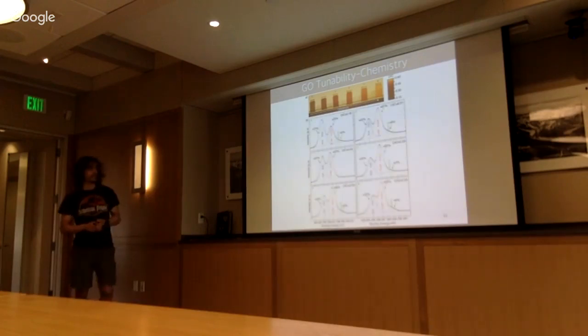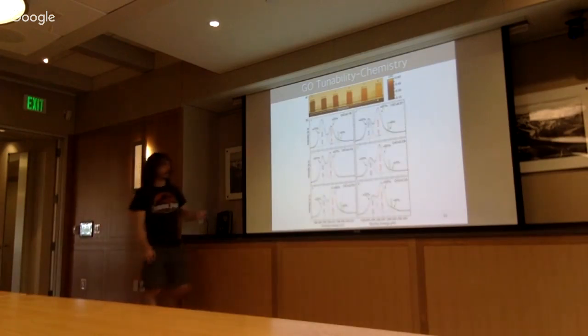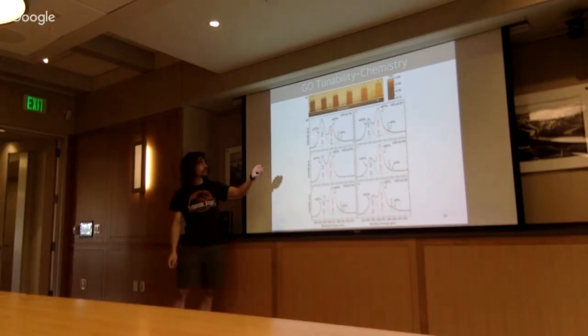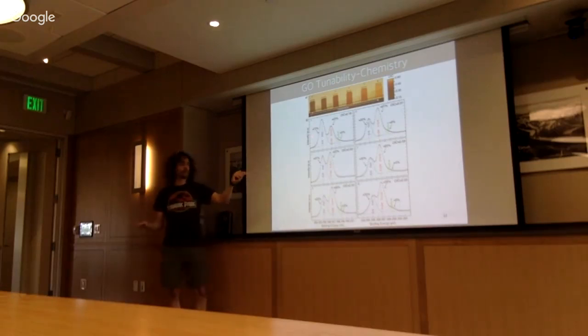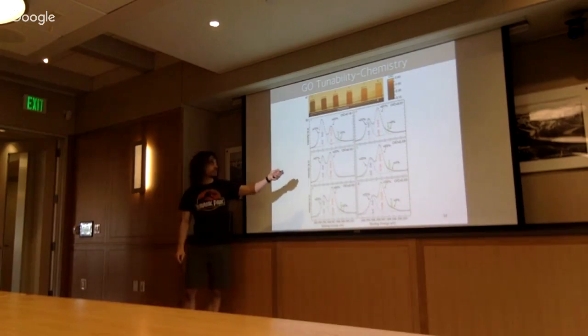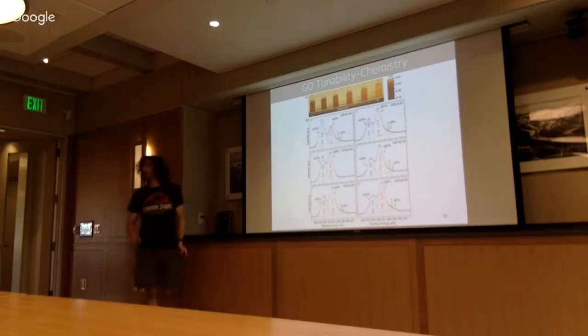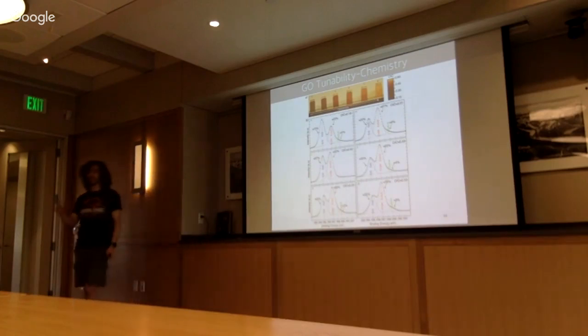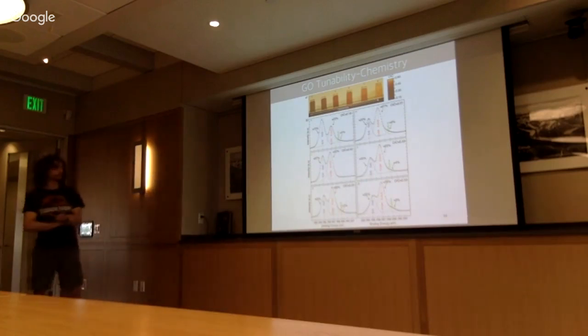And we can check the XPS spectra. What we can see here is that if you go from sample 1, which is low oxygen, to sample 6, high oxygen, just have a look at this central peak, and you can see that it's increasing. And this central peak is mainly due to the epoxide and hydroxyl functional groups.